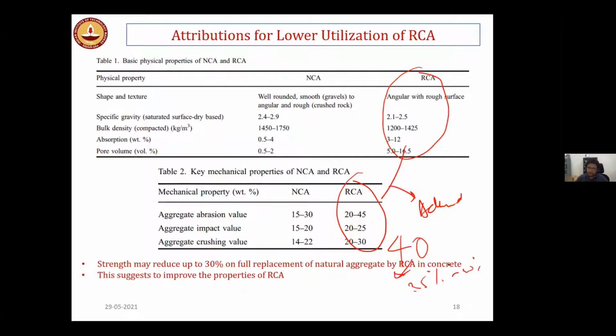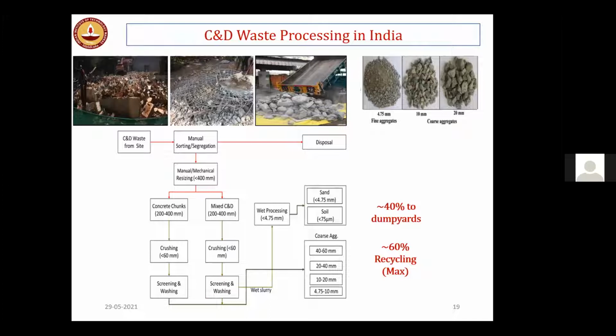But why is it happening? Because of the adhered mortar. That means it is time to improve the properties of the recycled concrete aggregate, right? If you are able to improve the physical properties of the recycled concrete aggregate, definitely we can increase the proportion of the aggregates for structural applications. So there are various means on how to do it. Rohit will be talking about how to address this adhered mortar. But what I suggest is that at the source only, we can reduce the adhered mortar content.